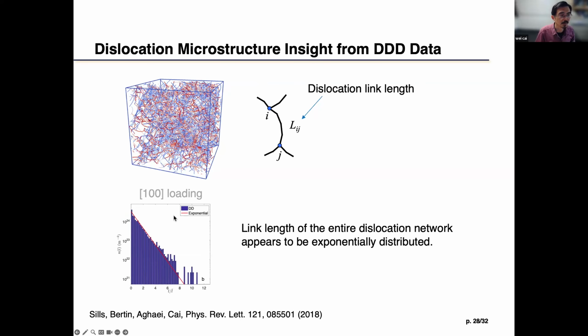So we know that dislocations form a network, and this network you can consider as nodes connected by links, which are like arms, or edges. And the edges have length, physical length. A while ago, my former student Ryan and I found from our first set of big simulations that the length distribution appeared to be an exponential distribution, because it's a straight line on a semi-log scale.